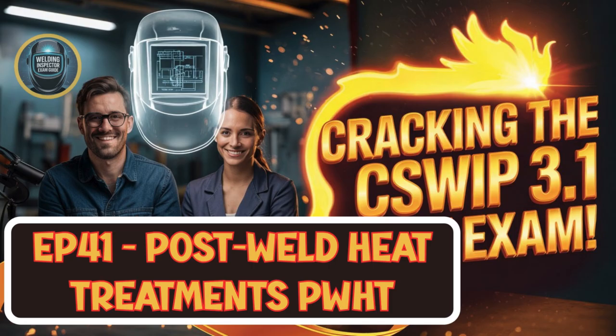Right, good question. Yeah. There are really 2 main ways it's applied, depending on the job. You've got global PWHT. This is where the entire component or a very large section of it is placed inside a furnace. These can be huge, often fired by gas or oil. Couple of key warnings here, though. You absolutely cannot have the burner flames directly hitting the metal part. That creates intense local hotspots, exactly the kind of thermal gradient you're trying to avoid.